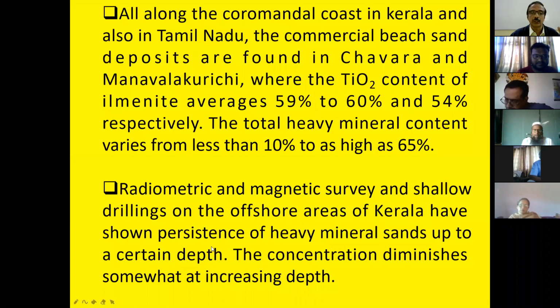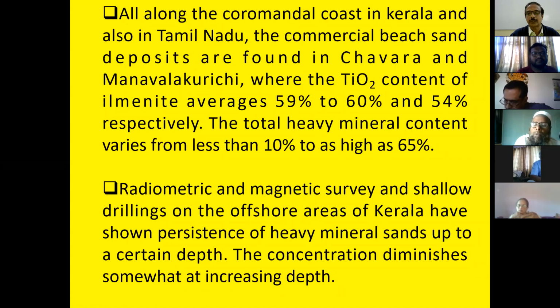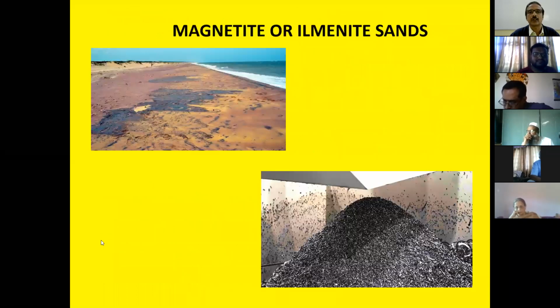And they have drilled such areas in the coastal regions, and found that up to some depth this material occurs along with the sand, which are called heavy mineral sands, up to a certain depth only. As you go deeper and deeper, the concentration of these heavy mineral sands, like ilmenite or magnetite, diminishes. That means it is a shallow mineralization that is found in the coastal areas. So these are all the magnetite and ilmenite sands that have been recovered in the coastal areas.